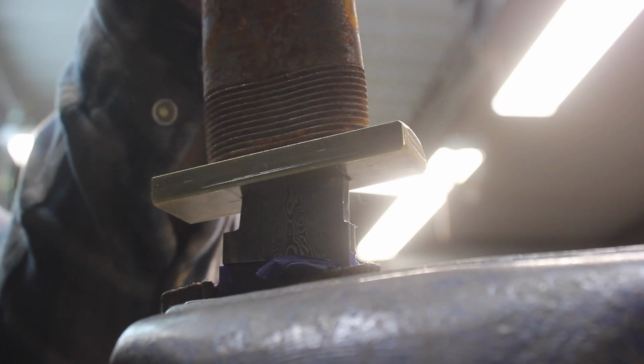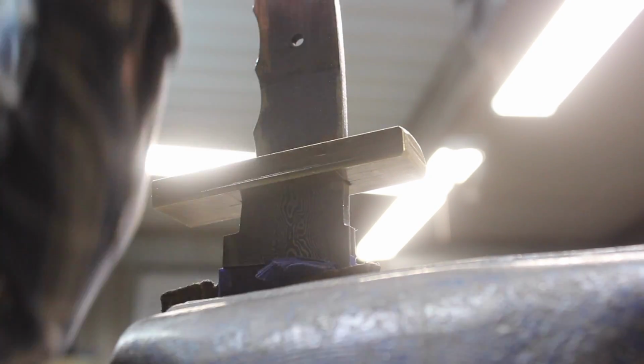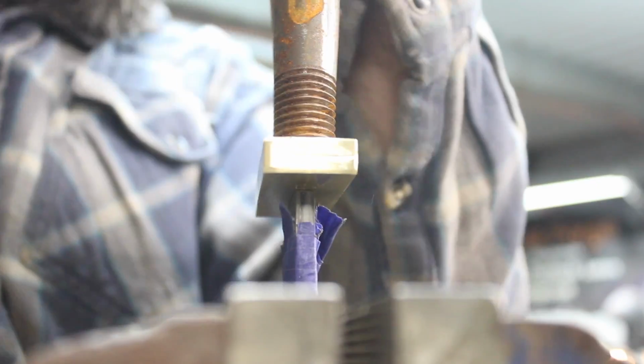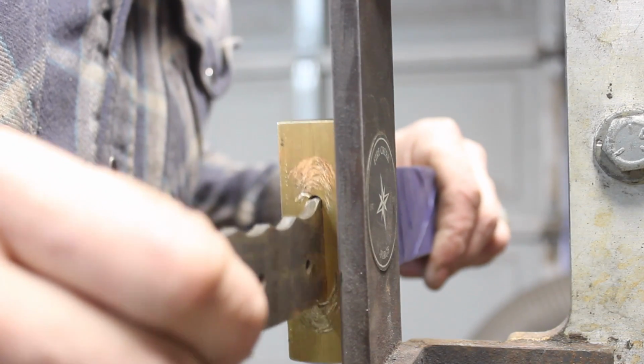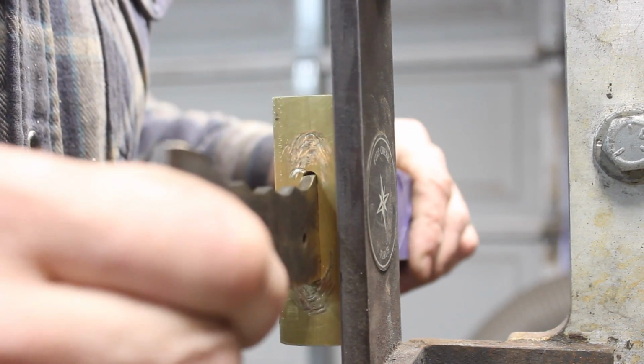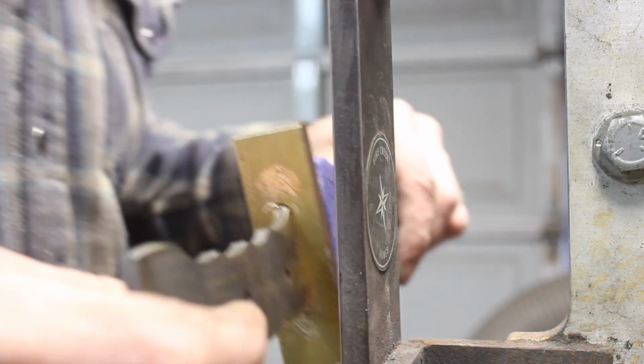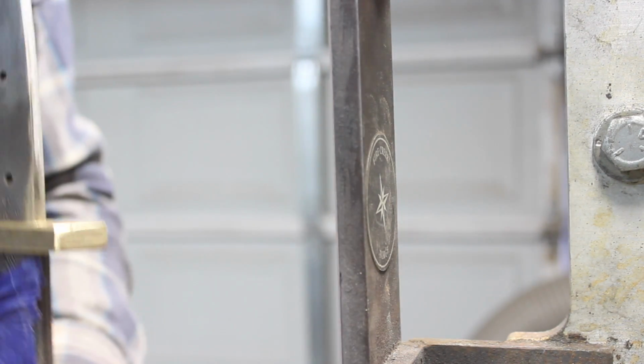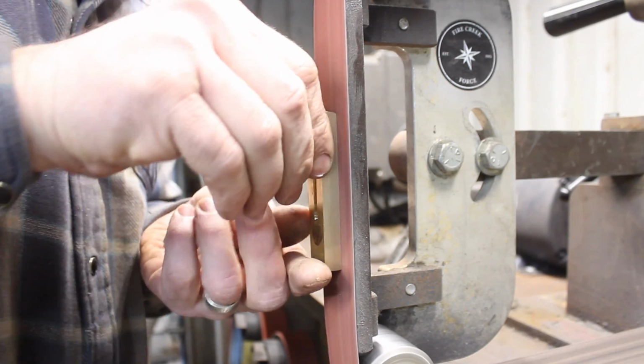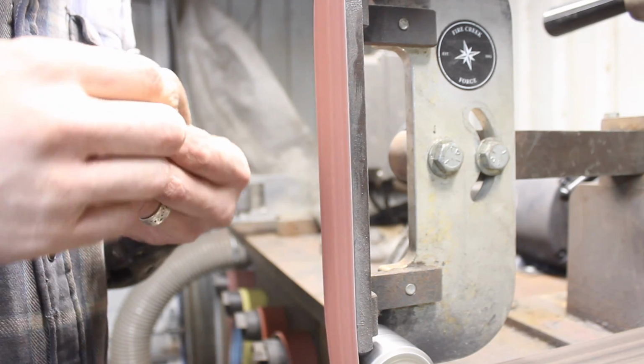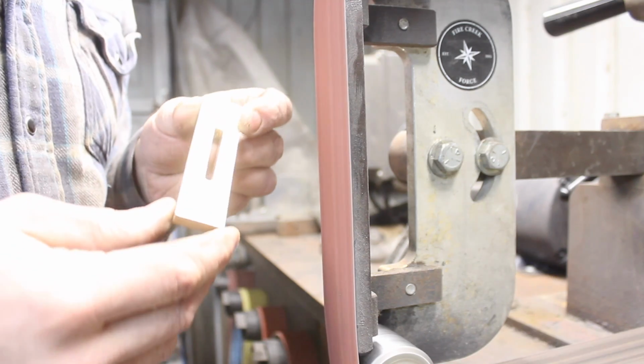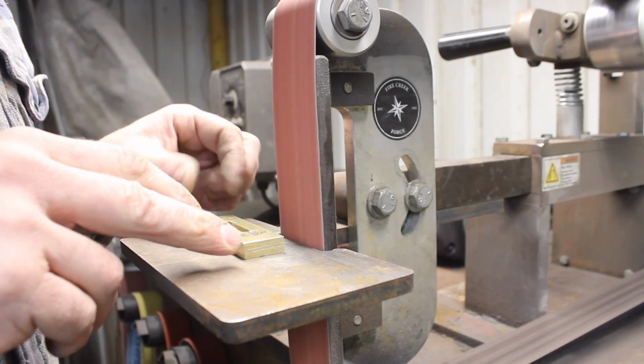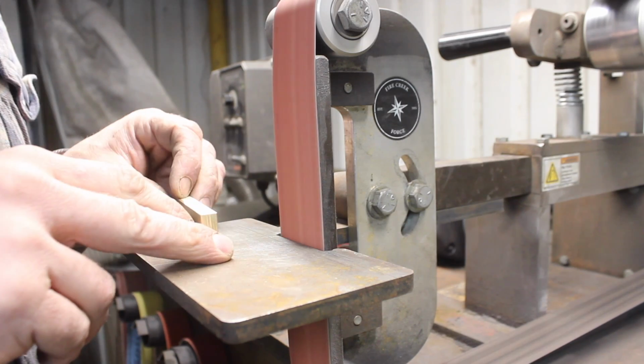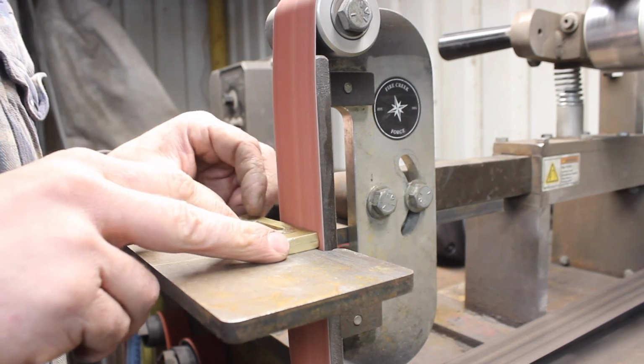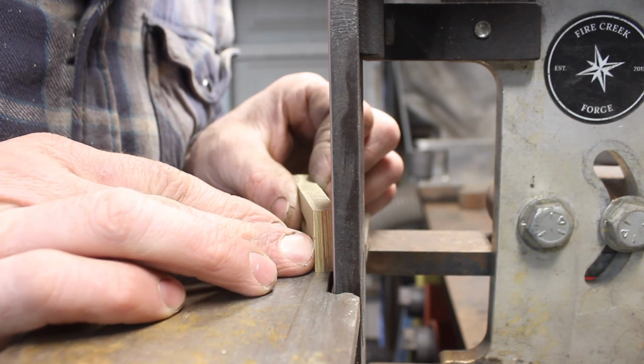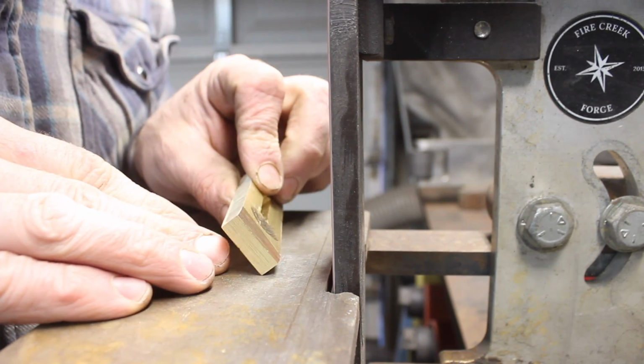You want it to be a tight fit, or at least I prefer a fit that you have to drive on slightly, but not to the extent that you start deforming things and create an overly tight fit. So snug, I guess, is the word. Once I got it fit on there, I hammered on the sides a little bit to tighten the slot up just a touch, and now I'm cleaning up those hammer marks and thinning the guard down just a little bit, getting things squared up. And the design of this guard is tapered a little bit on the ends, and so we'll go ahead and grind that in at this point.